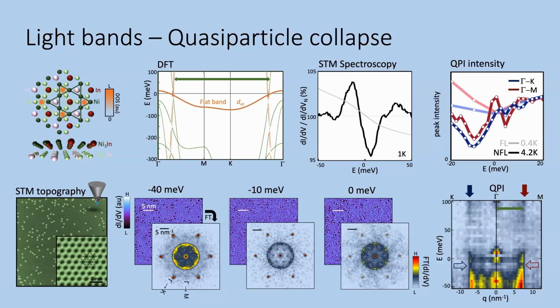So here we are imaging not the flat band. With QPI, we're imaging the light bands, those Dirac bands. And for a long time, we thought they are just spectators or a nuisance in this experiment. But actually now what we understand is that their interactions with the flat band is basically what gives rise to the strange metal. Because many of the material searches look for flat band materials, kagome metals that have flat bands at the Fermi level, it is important to remember that if you want to see strange metal-like behavior, you must also have a metal in your system.